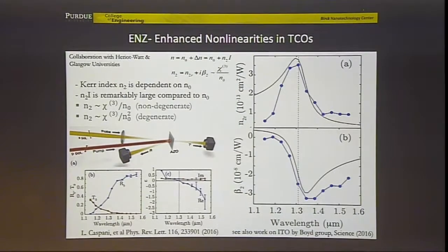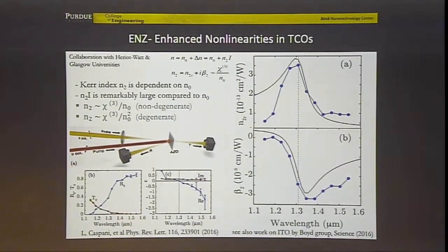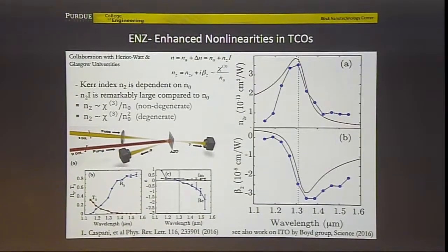The whole perturbation theory stops working. And moreover, this nonlinear term is enhanced because the linear refractive index is small. This is what I call a new branch of nonlinear optics, when you have enhancement of nonlinear response because the linear index becomes small. And sure enough, there are such materials, and that's what Sasha actually developed, so-called transparent conducting oxides, and specifically aluminum-doped zinc oxide.